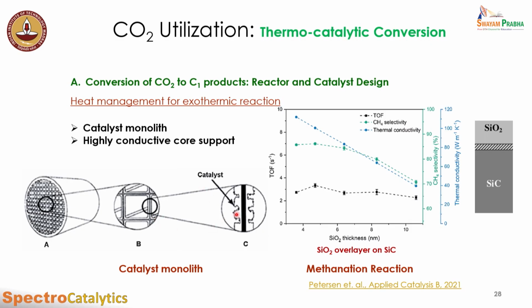On those microchannels, we can deposit catalysts such that the catalysts are not in a packed bed, but rather in a very porous media kind of thing. Then the convective flow of the reactants and products through these channels is so efficient that it can take out the heat being generated during the reaction on these catalyst particles. The other way is that we can have a very high conductive base on which we deposit our catalyst.